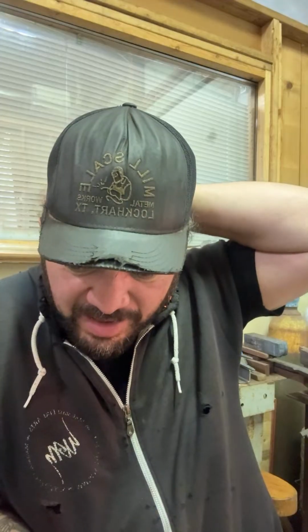It's like 99.9% of the forge scale was cleaned off, but there's still just this tiniest little bit. But that's because I know that in this process of coming up to temp, soaking at high temp, and then setting the weld, it's going to give it time to clean itself out. And that's how I do it all the time these days. Now, if I'm getting closer to my final weld, like actually this next phase of forge welding is going to be the last forge weld,